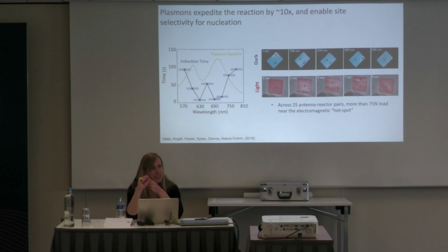So one of which is that the light is being absorbed, but instead of giving rise to heating and expansion of the lattice, it gives rise to those hot carriers that basically get quickly ejected or extracted from the nanoparticle and put into basically the LUMO of that hybrid hydrogen-palladium orbital that forms on the surface of the nanoparticle. So that's kind of one thing that's happening. There's not so much lattice heating in phonons, but there are hot electrons, so hot carriers.